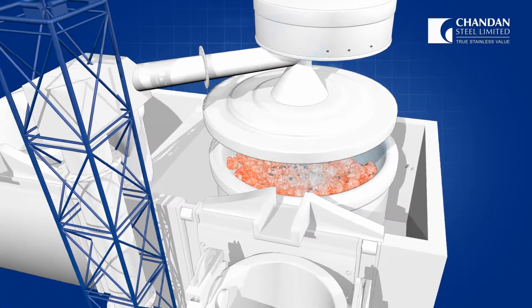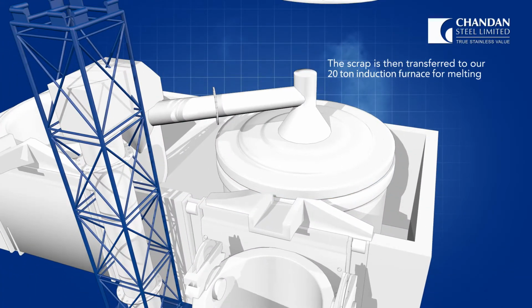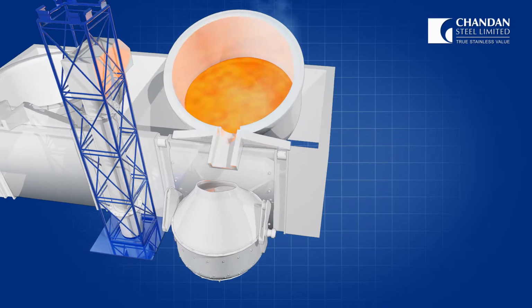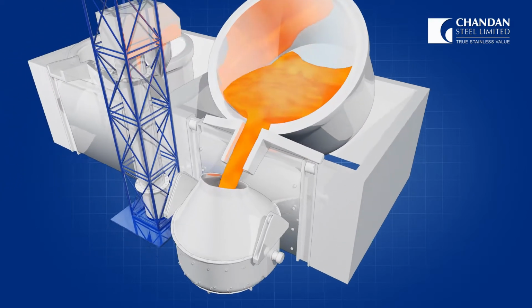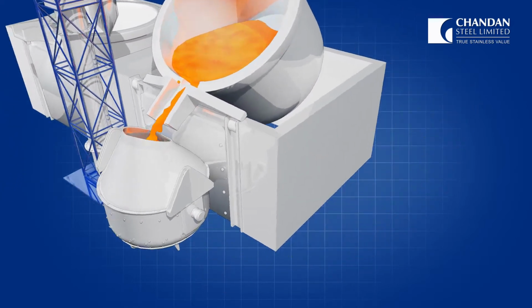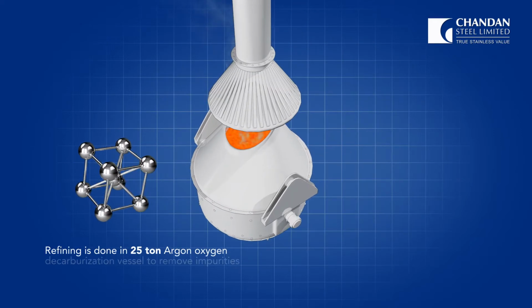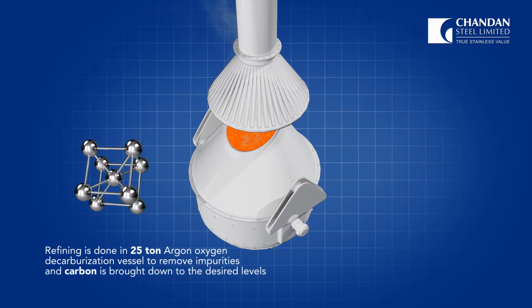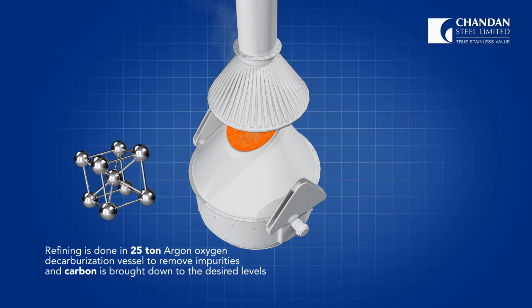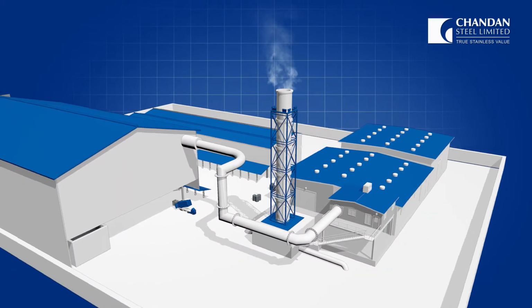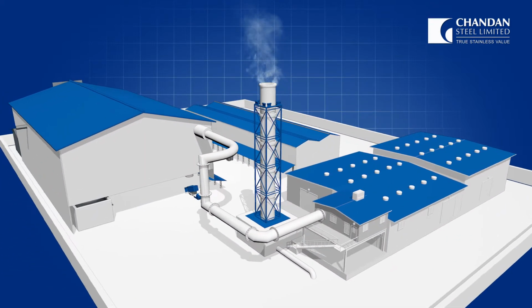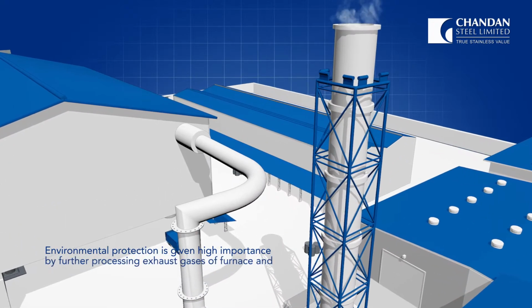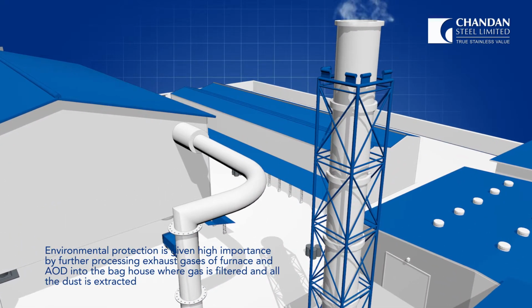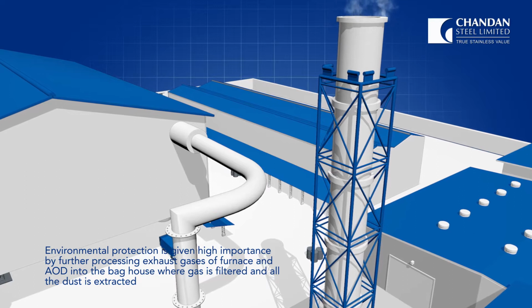The stainless steel scrap is then transferred to 20-ton induction furnace for melting. Refining is done in 25-ton argon-oxygen decarburization vessel to remove impurities, and carbon is brought down to the desired levels. Environmental protection is given high importance by further processing exhaust gases of furnace and AOD into the bag house, where gas is filtered and all the dust is extracted.